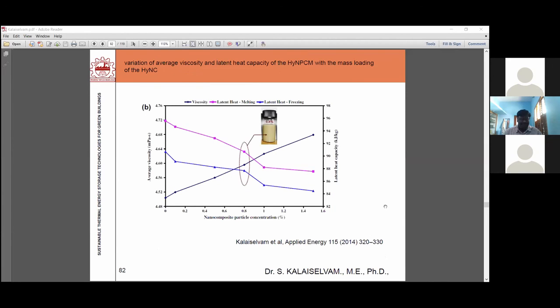So you may have a doubt: when adding this nanomaterial, at what proportion are we supposed to stop? For that, this is the viscosity curve, and this is the latent heat curve, the latent heat of melting and the latent heat of freezing. At one particular point, they will meet. At that proportion, it will give good results. Beyond that, there may be possibilities of aggregation, or the results may not be good.